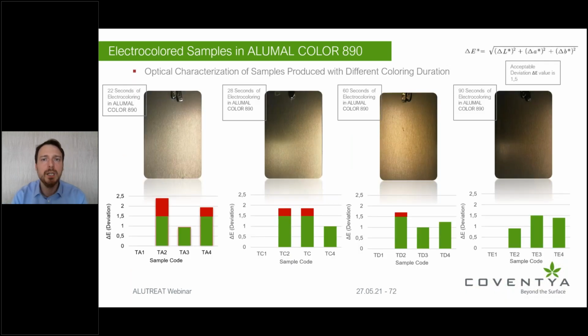So here you can see with the tin-based coloring, as the time of the process increases, the darker colors, as we have seen, are much more stable in terms of delta E, whereas the lighter the shade, the worse it gets, and you have much more deviation because, quite frankly, it is a faster process. Like here for very light champagne, it's only 22 seconds.